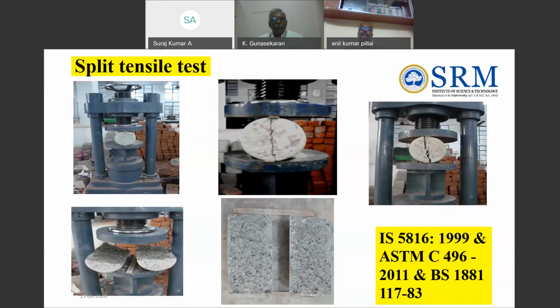While doing this test, many people normally place the packing strip at both top and bottom of the specimen. People think this is simply to keep the specimen in the right position. That is not the case actually. There is a technical reason for that. The reason is when you apply a load by keeping the cylinder in a diametrical manner, the loading condition produces a high compressive stress immediately below the two generators to which the load is applied, that is top and bottom. But the large portion corresponding to the depth is subjected to uniform tensile stress acting in the horizontal direction. So they estimated that the compressive stress acts for about 1/6 of the depth, and the remaining 5/6 depth is subjected to tension.